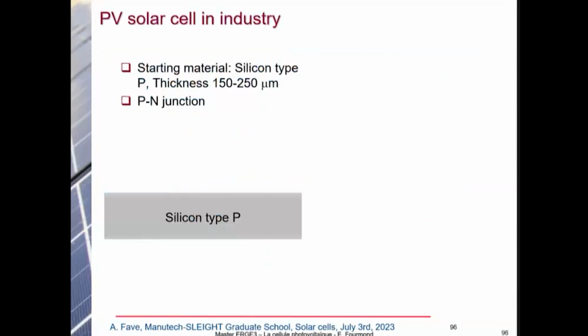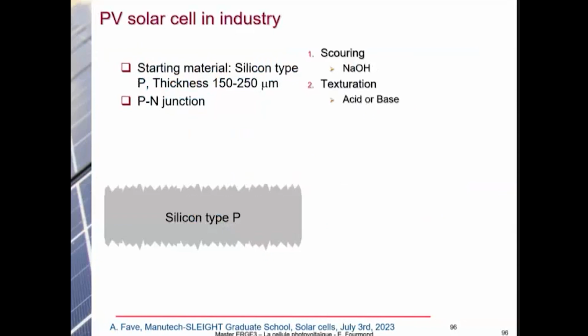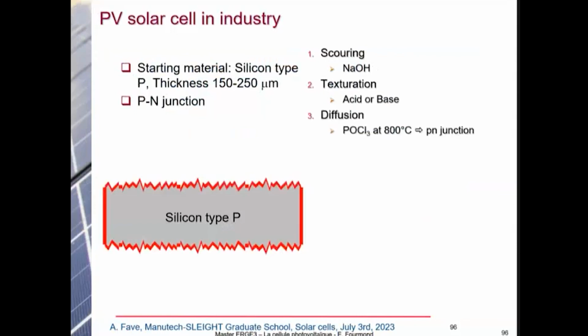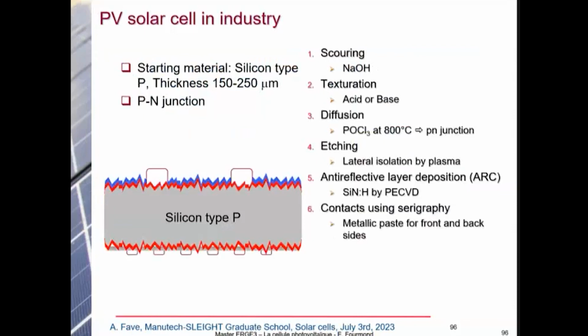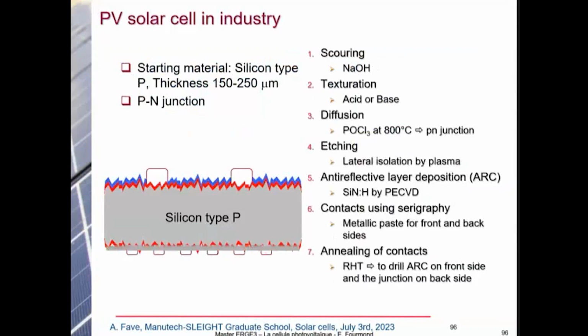How do we fabricate the solar cell from the wafer? So first, you clean the wafer after slicing it. You make texturation. It uses a chemical way. Then you diffuse some phosphorus into your P-type silicon in order to get the PN junction. You etch the edges to isolate your PN junction here. Then you deposit anti-reflective coating. Then you deposit your metallic contact and you heat up and you anneal the contact. So on the back side, you have aluminum. So aluminum, it's P-type material for silicon, and it will compensate the N-type material that was here before. Okay.